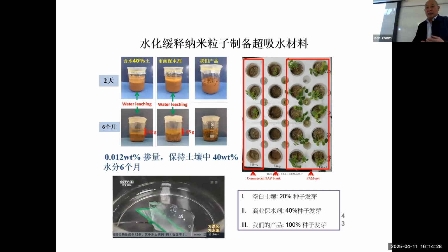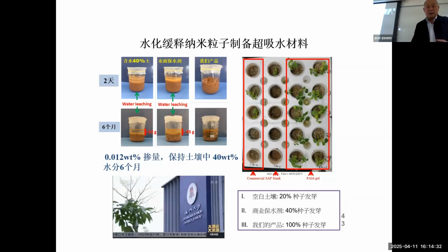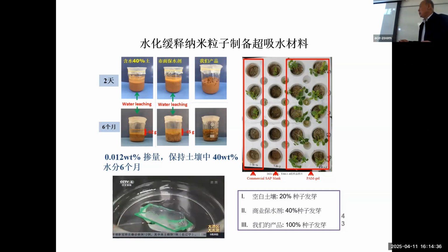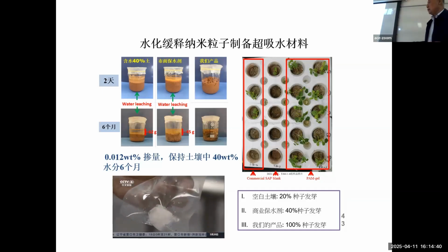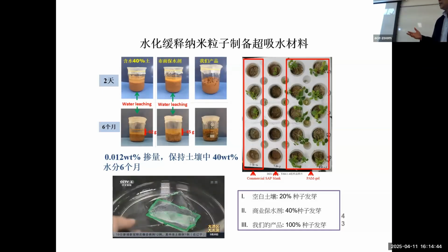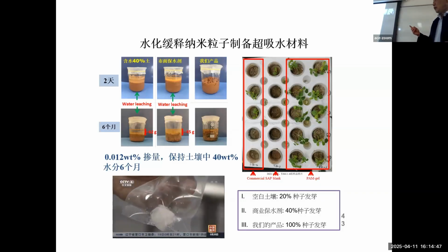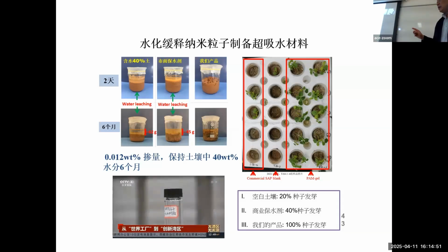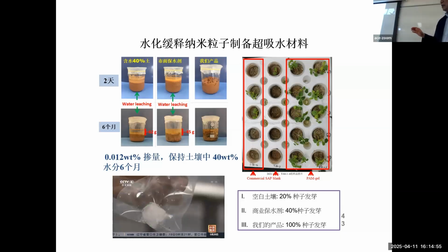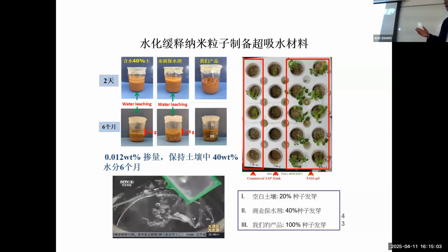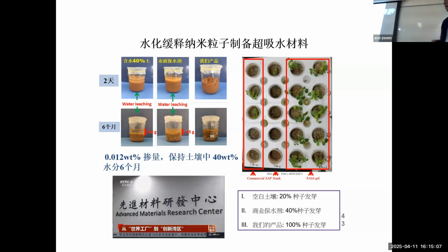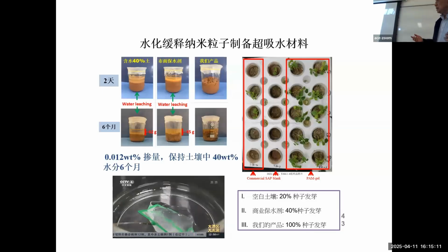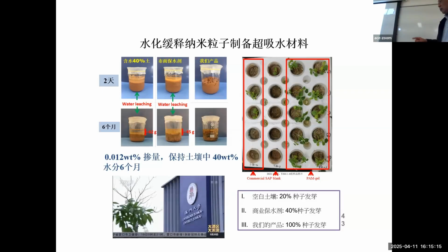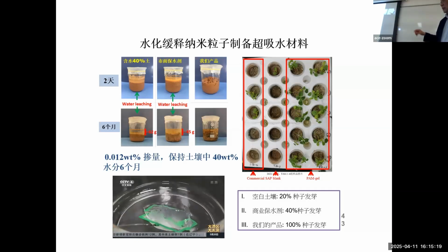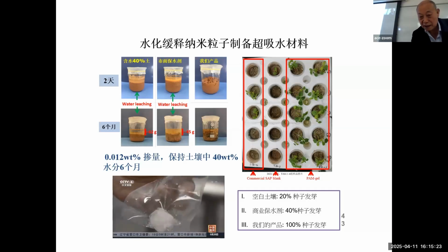So one application is that we can use that for soil improvement. So we put some of our generated hydrogel and the commercially available gel and some without handling. So you can see, for our hydrogel it keeps about 40% of its water in 6 months, but the other. And also for the plant, without the hydrogel, it is basically very difficult for the seed to turn green, and commercially available is only about 40%, but for our hydrogel modified about 100%. So this is that.